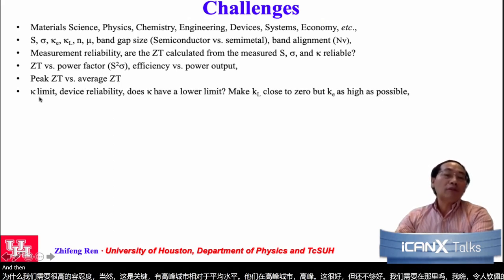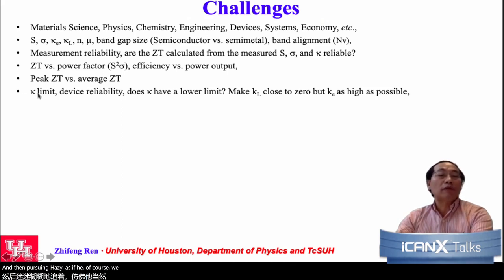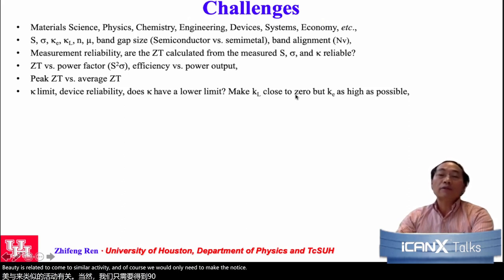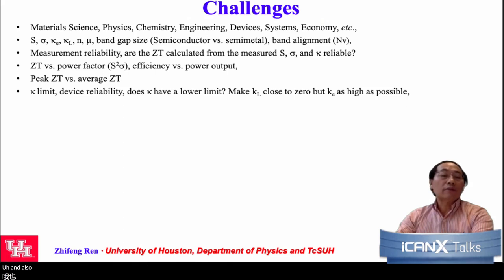And then pursuing high ZT, of course, we pursue very low thermal conductivity, but the thermal conductivity does have a limit because the device reliability is related to total thermal conductivity. And of course, we would like to make the lattice thermal conductivity as close to zero as possible, but the electronic thermal conductivity has to be as high as possible so that we have high power factor and also higher output power. That's what we needed.